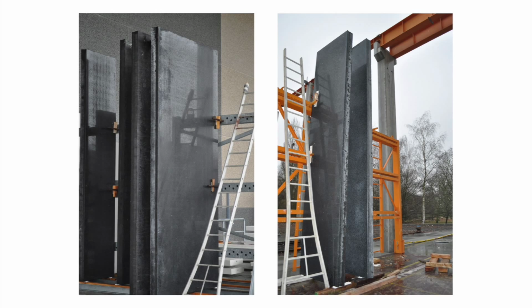And on the top of the staircase, we wanted to get a very simple profile detail. Often you knock the tops off concrete to make sure it doesn't get damaged, but we inserted a little moulding into the formwork, so when it was pulled away, you had a very nice ridge detail which protected the main wall, but gave the concrete a subtle detail at the top, which was actually quite sophisticated, and it's really just achieved by a 10 by 5 mil batten applied to the plywood.